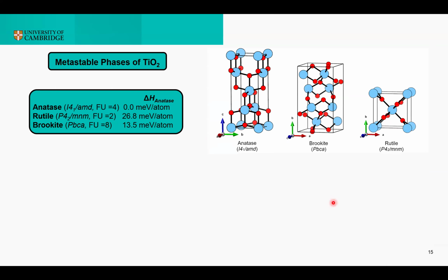But now, some results. So the first test that I decided to run was on the metastable phase of titanium dioxide that is called brookite. So brookite is not the least stable among the known polymorphs of titanium dioxide, at least at ambient conditions and according to DFT or PBE-DFT, but it is the least symmetric. And sometimes it is problematic to find with the classic crystal structure predictions.